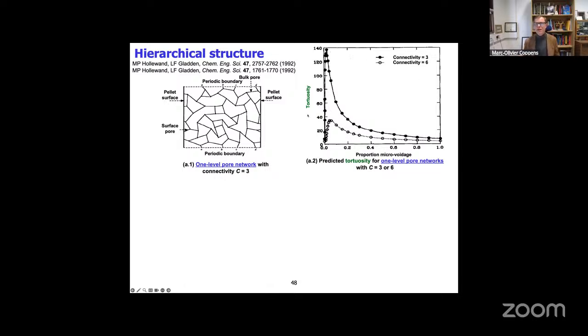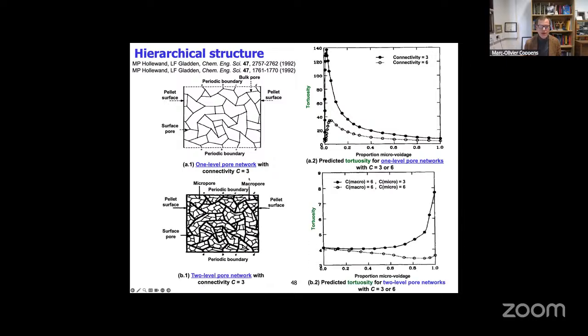These numbers are clearly unrealistic. I mean, they are not being measured. And the problem is that a lot of the pore network models, as they were used, and quite a few still used today, are so-called one-level pore networks. This is not what you see in reality. Typically, you have an image like that where you have several levels.